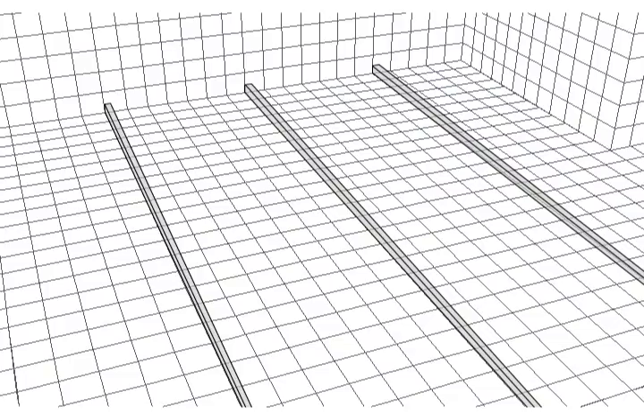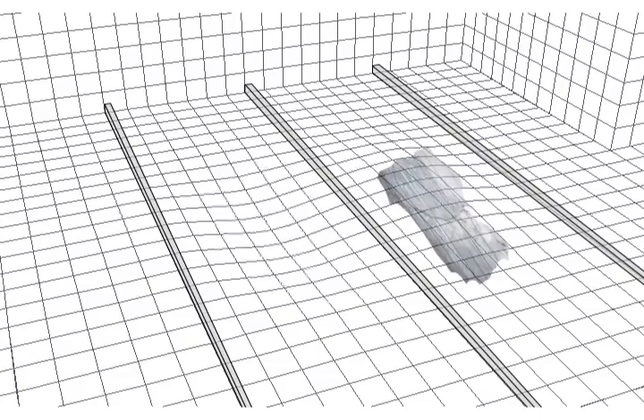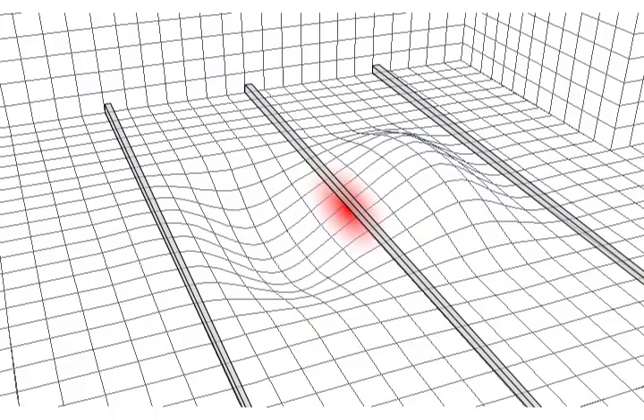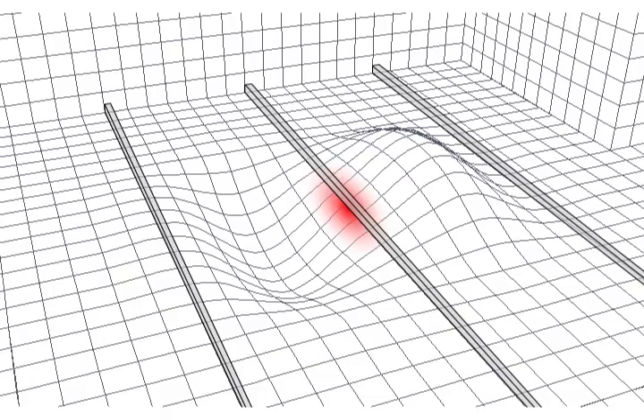The first general process involves what investigators refer to as the continuity effect — a physical condition where a deformation inward results in a corresponding outward deflection in the immediate area next to the inward deflection. The interface area where these two deflections occur in opposite directions becomes the origin of locally strained material, resulting in a weakened area in the tank bottom due to the highly strained condition.